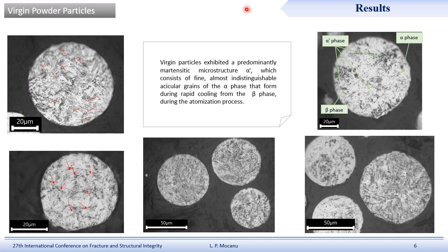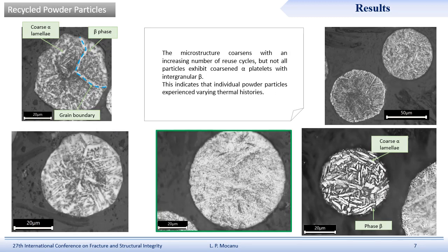Then in this work we analyzed the microstructure, and we saw that the virgin powder is characterized by a martensitic microstructure, and this is due to the fast cooling rate during the atomization process. Regarding the recycled powder, we saw that most of them exhibit a alpha-beta microstructure, as can be seen here, and this is due to the lower cooling rate during the production cycle. But not all the particles exhibit the same alpha-beta microstructure, as can be seen from these particles highlighted in green.